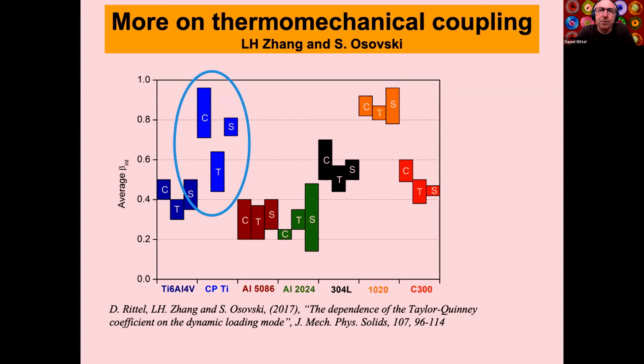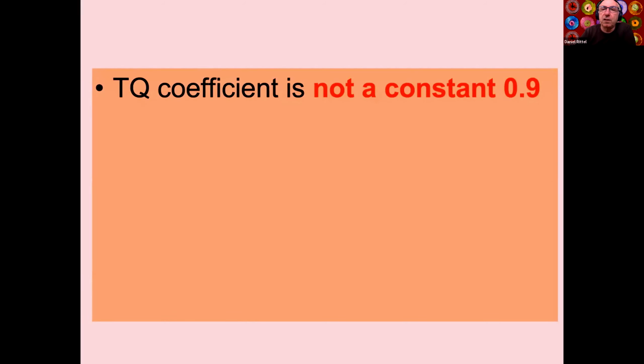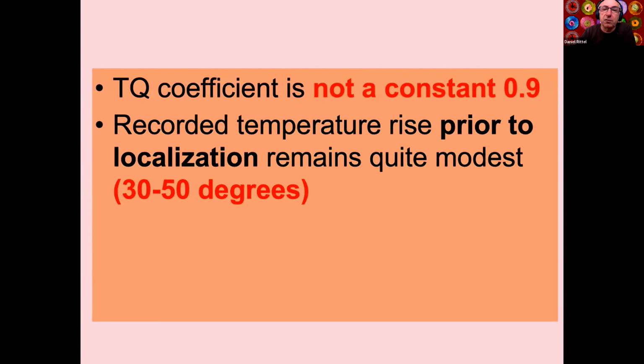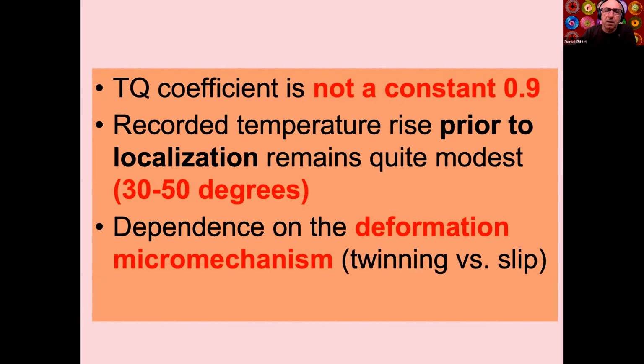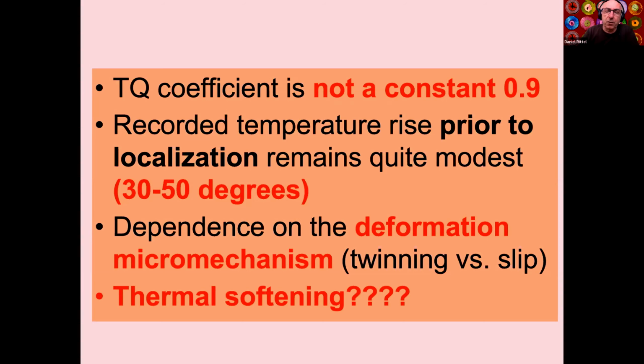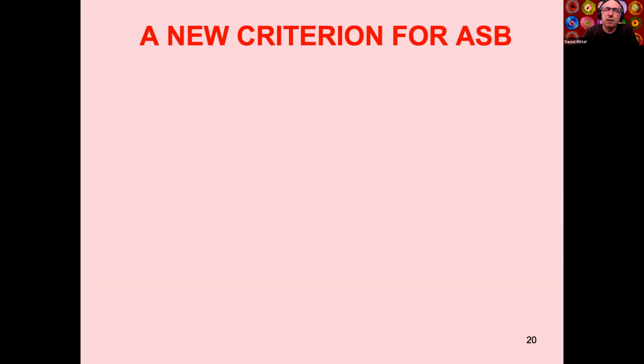So if you add to that that this coefficient may be, or is, rate and strain dependent, then your heat equation becomes nonlinear. The coupled heat equation becomes nonlinear, where you need a separate equation for your thermomechanical conversion, and things become interesting. So we said the Taylor-Quinney coefficient is not a constant 0.9. The temperature recorded prior to localization remains quite modest, of the order of 50 degrees. That's not very significant to soften the material. And there is a strong relation with the mechanism of deformation. Would it be twinning or slip, or both? Thermal softening, question mark.